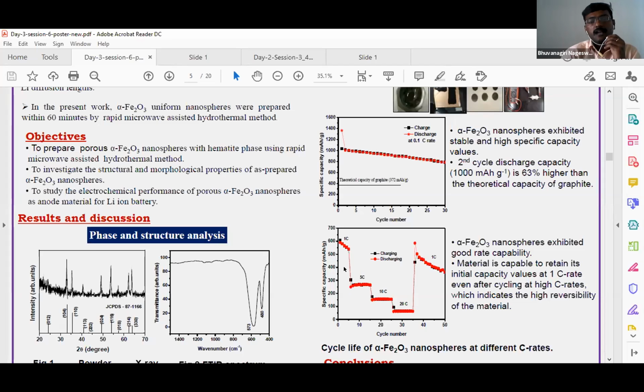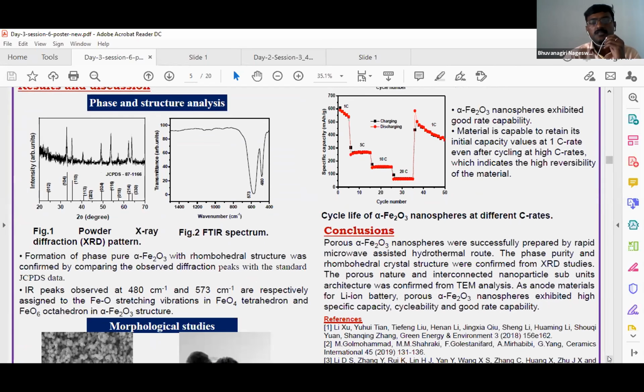In the first cycle, discharge capacity is high compared to charge capacity. This irreversible capacity loss is mainly due to the decomposition of electrolyte in the beginning of the cycling. But from the second cycle onwards, we can see both the capacity values are identical to each other, which indicates good lithium insertion and de-insertion into the Fe2O3 structure. In the second cycle, it exhibits a capacity around 1000 milliampere hour per gram, which is 63% higher than the graphite used in commercial lithium-ion batteries.